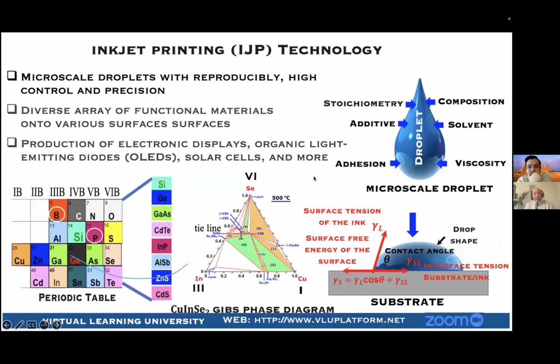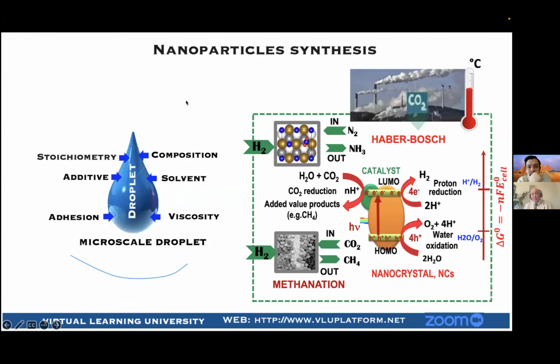Okay, as I told you, for example, in a droplet of the ink you formulate, you have to control the stoichiometry, the composition, the solvent, the additive, the adhesion, the viscosity. So it's really a very good topic to work on. And I work very much on this area here.